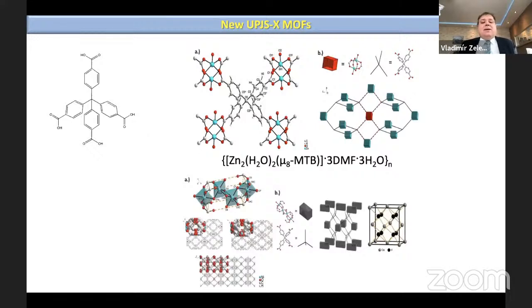In our department, we are working with MOFs, which we named UPJS. At present, we have 12 new structures, UPJS compounds. We use methane tetrabenzoic acid for their synthesis. Some of the structures are very unique because they imitate natural minerals. So it is a complex structure, but when you view this structure in some simple way, such a structure can imitate either diamond or fluorite, which is calcium fluoride. So they have some beauty from a scientific point of view, but also the structures are porous and they can adsorb different gases.